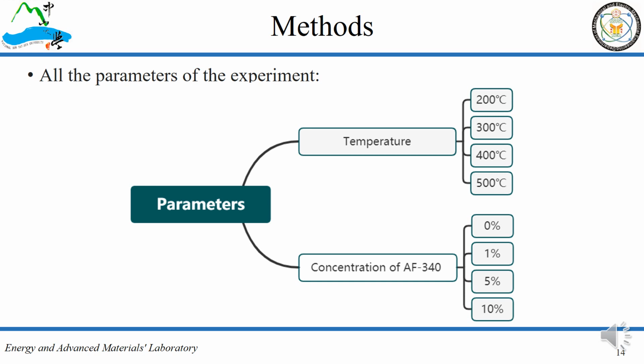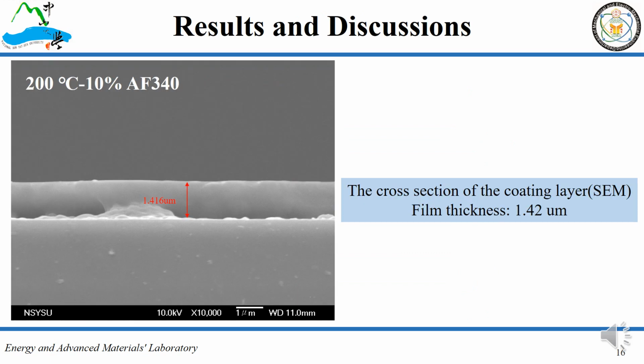This page shows all the parameters of the experiment. The pyrolytic temperatures are 200 to 500 degrees Celsius, and the concentrations of AF340 are 0, 1, 5, and 10% respectively. The picture shows the thickness of the coating layer is 1.42 micrometers, at a pyrolytic temperature of 200 degrees Celsius and a concentration of 10%.